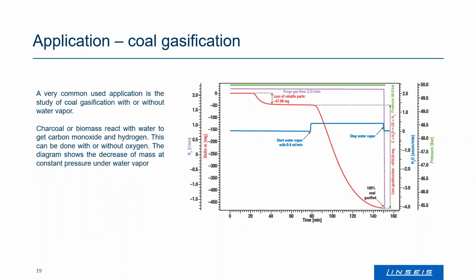So what you do is you heat up your system to a temperature of maybe 300, 400 degrees centigrade, and during heating you lose a lot of volatile components. Usually it's done in inert gas at the very beginning. In that example, the complete setup was done under nitrogen gas. The sample was heated. The red curve shows the mass loss.